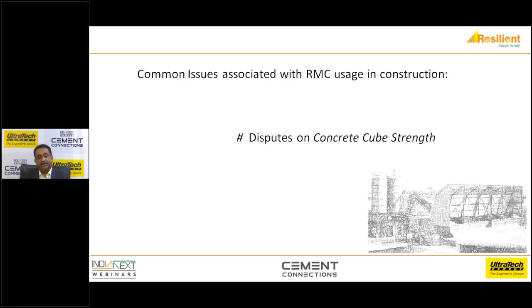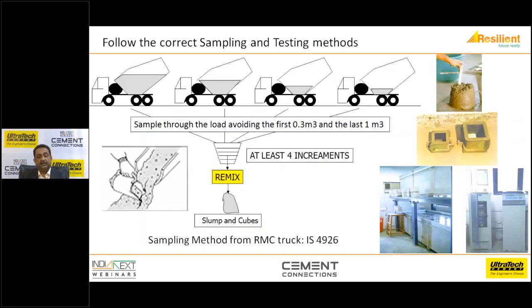The next common issue, which is a big problem, is the concrete cube testing. Quite often, you get disputes between the concrete supplier and the customer, saying that there's a big mismatch between the concrete cube results. Before we get into the cube results, one of the most important factors to keep in mind is that you are sampling and testing the product right, and that the test results you get are a true reflection of the concrete that has been supplied. The Indian Standard 4926 very clearly tells you the right method of sampling.